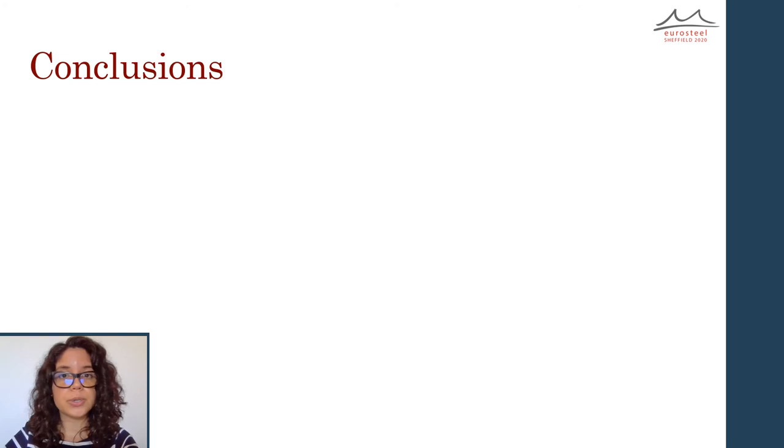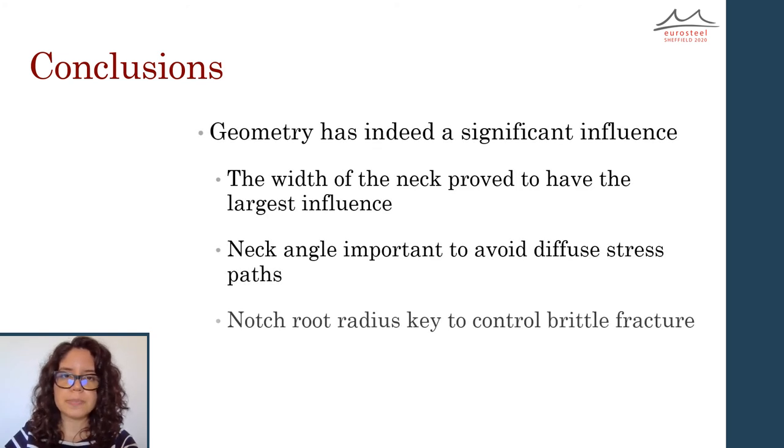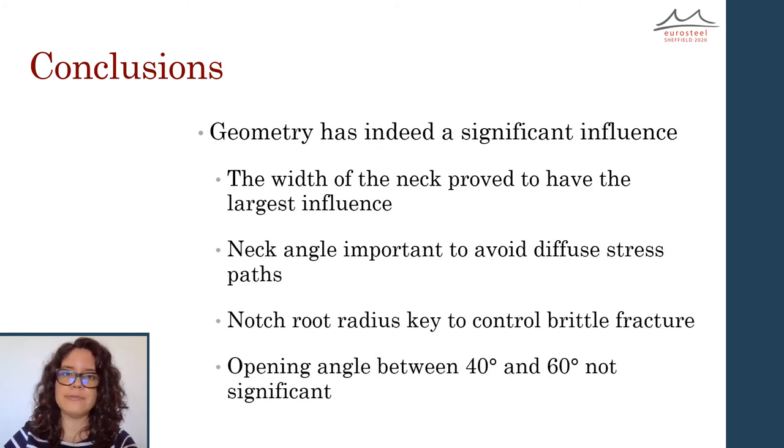Finally, it was possible to confirm that the geometry of the specimen has a significant influence over the dispersion of the results, especially the width of the neck. We also discovered that the neck angle plays an important role when trying to avoid diffuse stress paths, that the notch root radius is key to control the brittle fracture, and lastly, that opening angles between 40 and 60 degrees do not have a great impact on the results.